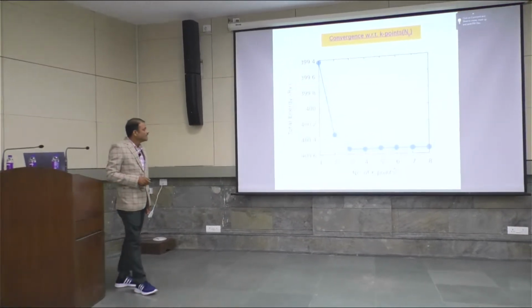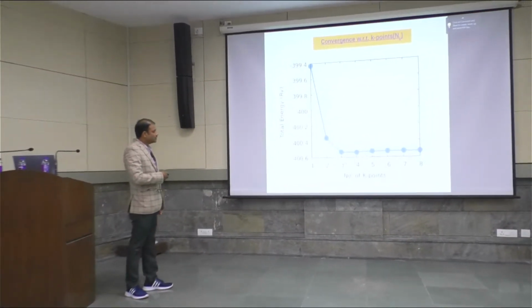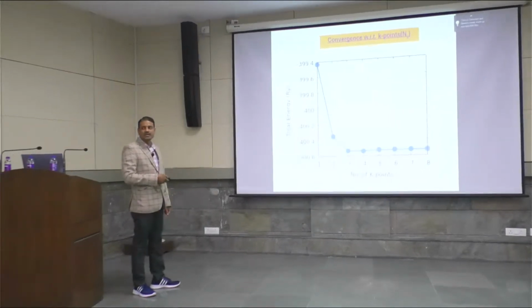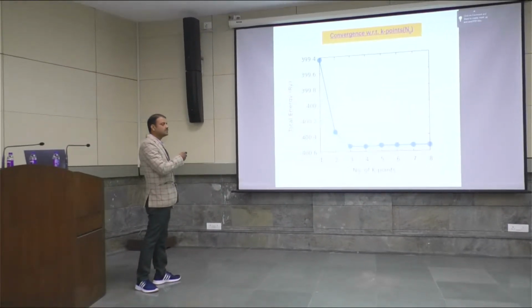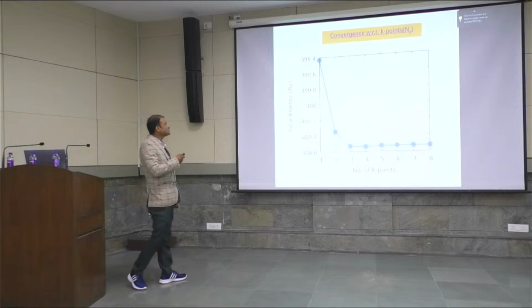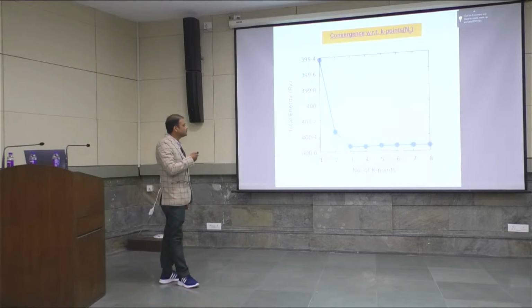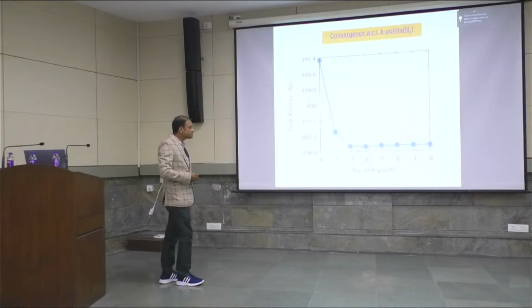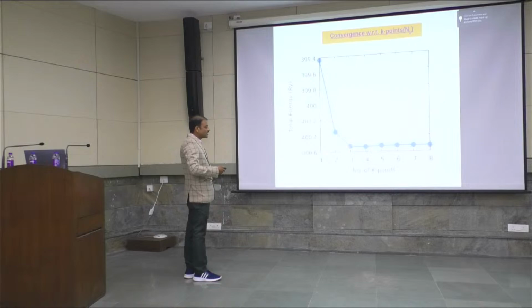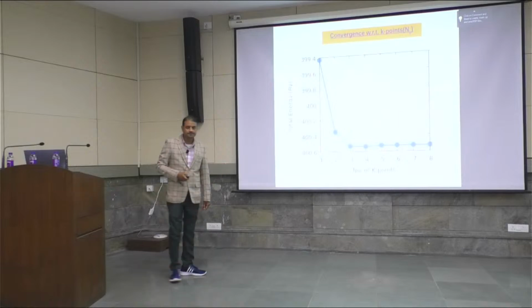So here, with increasing number of K points, the total energy of the atom is plotted. And we see that the energy initially starts decreasing and after some point, it is getting saturated. Straight curve. So we can see that it is not getting higher or lower value. So in between, any value can be chosen for the calculation. So in general, I have taken 6.